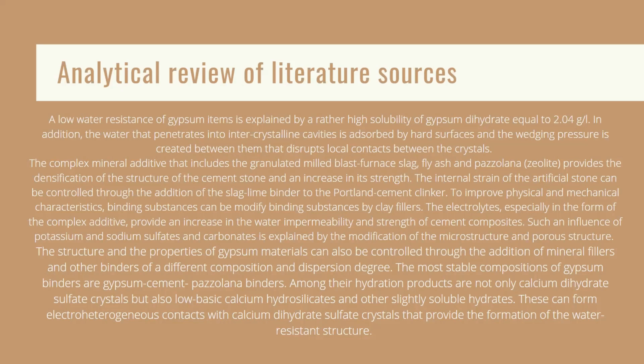The most stable compositions of gypsum binders are gypsum cement pozzolana binders. Among the hydration products are not only calcium sulfate dihydrate crystals, but also low basic calcium hydrosilicates and other slightly soluble hydrates. They can form electroheterogeneous contacts with calcium sulfate dihydrate crystals that provide the formation of the water resistant